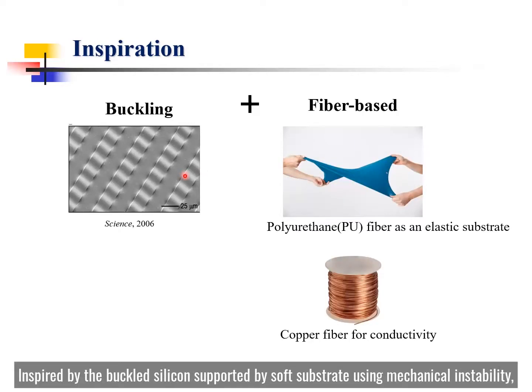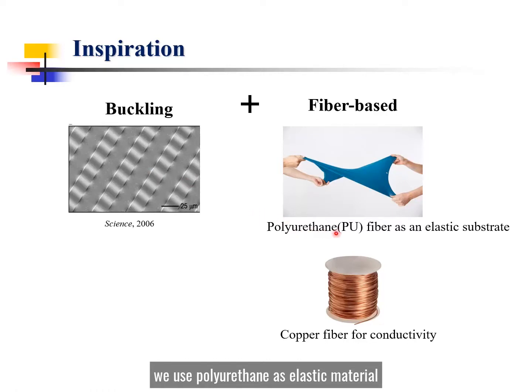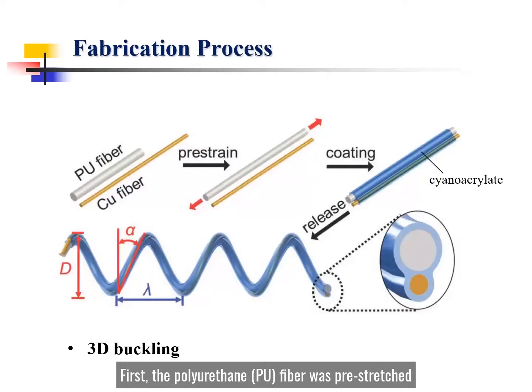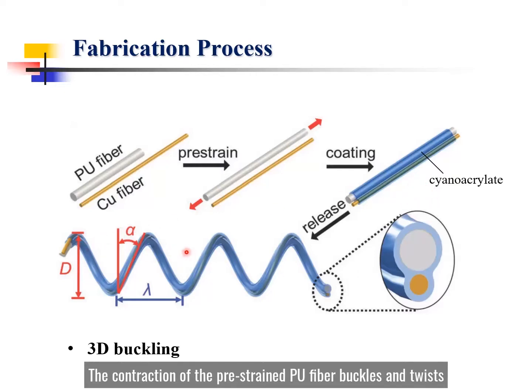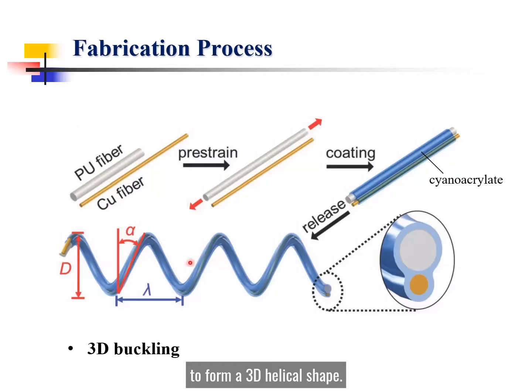Inspired by buckled silicon supported by a soft substrate using mechanical instability, we use polyurethane as the elastic material and copper fiber as the conductive material to prepare the fiber-based wearable electronics. First, the PU fiber was pre-stretched by a large strain ranging from 100% to 400%. Then it was coated with cyanoacrylate and bound with copper fiber with a radius of about 30 micrometers. The contraction of the pre-stretched PU fiber buckles and twists the fiber to form a 3D helical shape.